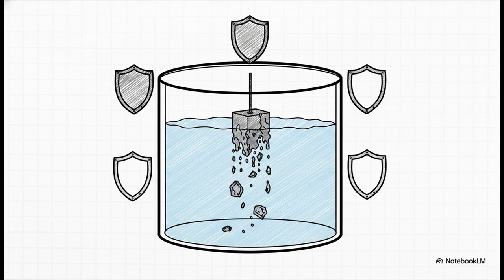But honestly, my absolute favorite method is something called cathodic protection. Remember how the anode always decays to protect the cathode? Well, engineers will literally suspend a block of a more reactive metal, something like zinc or magnesium, right inside the steel water tank. This new metal willingly volunteers to be the anode. It completely sacrifices itself, slowly dissolving away, just so that the entire steel tank becomes a protected cathode. It's a really beautiful, engineered act of chemical sacrifice.